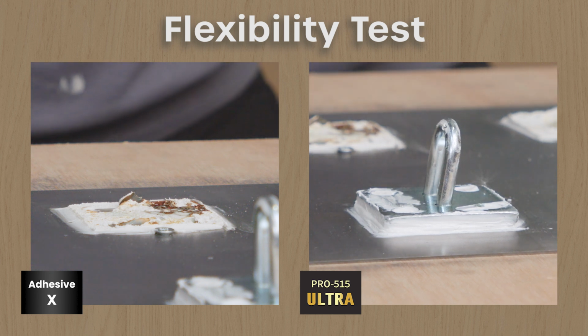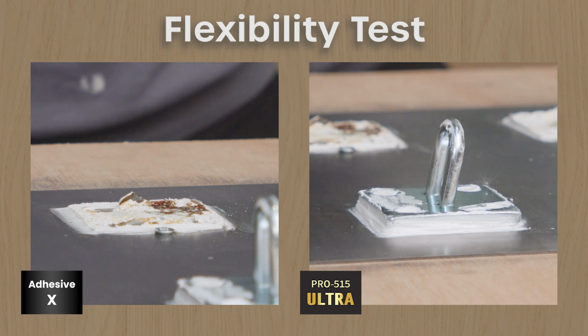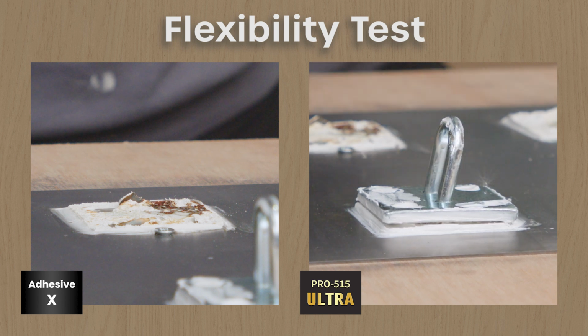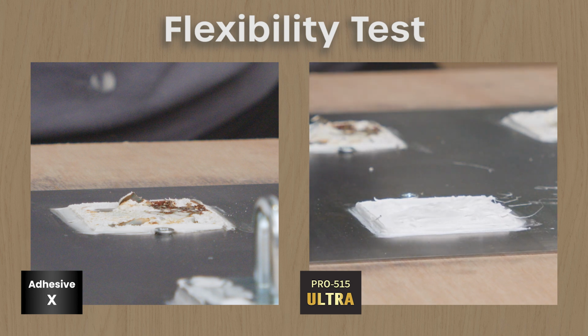Now this test displayed the true benefit of PRO-515's combined strength and flexibility. Repeated blows with the hammer caused the steel peg to bend under the force. 5 hard hits were required to weaken the bond before the adhesive failed and the peg came loose.